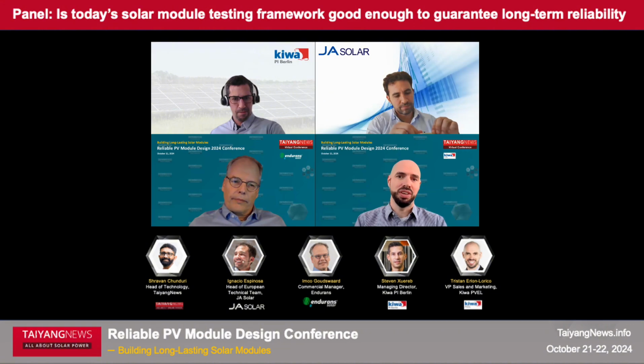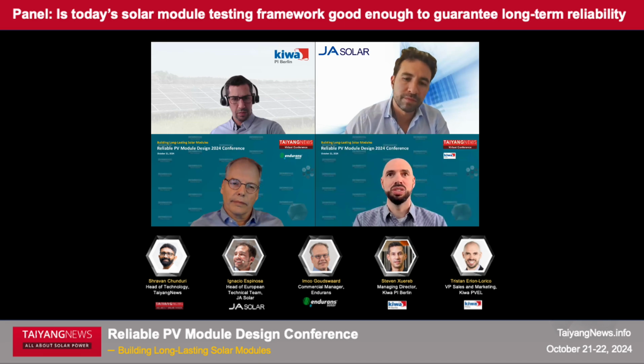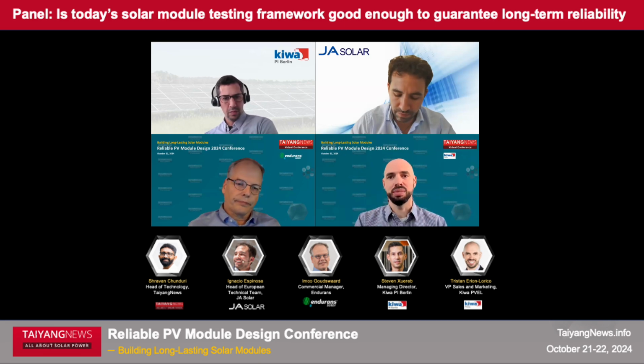Now we see more manufacturers, not as many as TOPCon, but some manufacturers move into the HJT space, and there's a lot to learn. It's a different module technology. As I mentioned in my presentation, the soldering is low temperature, and it's more susceptible to moisture and other degradation mechanisms. And similar to Panasonic, there's manufacturers that can make a very reliable HJT module, and there's others that are still earlier in that learning curve and need to dial in their process a bit more to have a more reliable module. And I think that's the fundamental thing we're seeing in HJT.